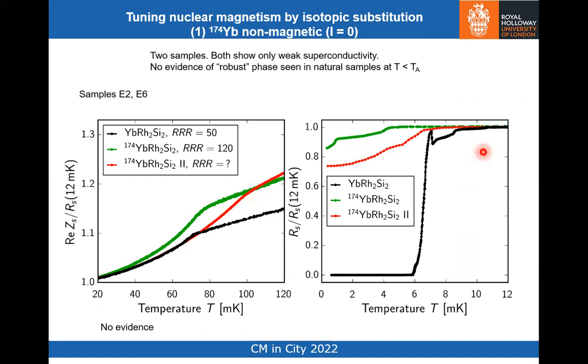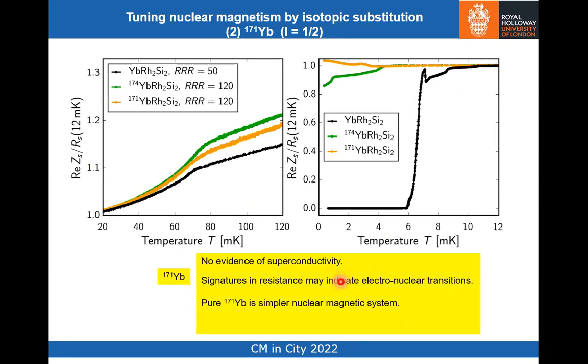Now, if we go to lower temperatures, this is the superconducting signature in the natural sample, and it also has, remember, this other signature at 1.5 millikelvin into this more robust state. And that signature into the more robust state is driven by the nuclear spins. And we see very, very weak effects in the 174 enriched samples, the two 174-rich samples. You notice that the temperature dependence of the resistance isn't the same for these two nominally identical samples. But they definitely aren't showing a transition into a robust superconducting state at 1.5 millikelvin. So that confirms this idea of the interplay between the change in electronic magnetism driven by nuclear magnetism coinciding with superconductivity at 1.5 millikelvin. And then here's 171.